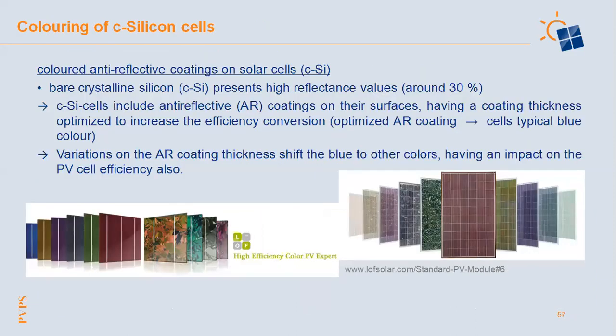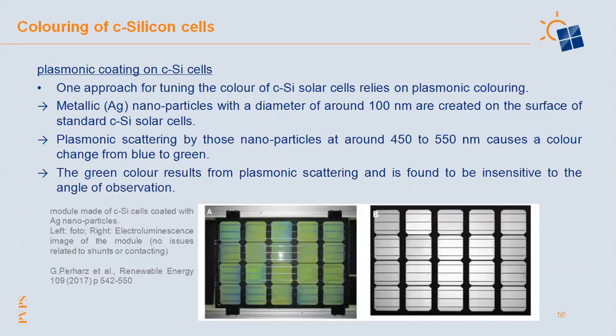Then the other way to color crystalline silicon cells is to have an anti-reflective coating on the cell with a special thickness. Nearly all crystalline silicon cells have an anti-reflective coating to decrease the high reflectance values. Usually the optimized coating has a blue color, which you all know from the mono and polycrystalline cells. But if you change the thickness of the film, then you can achieve a special color effect. The other way to color the crystalline silicon cells is plasmonic coating, where you have small metallic nanoparticles on the surface, and they give the color to your cells.